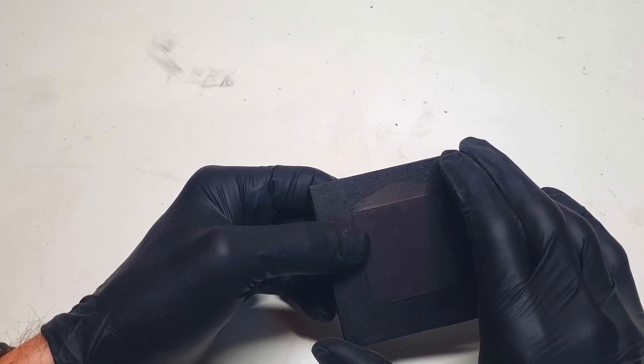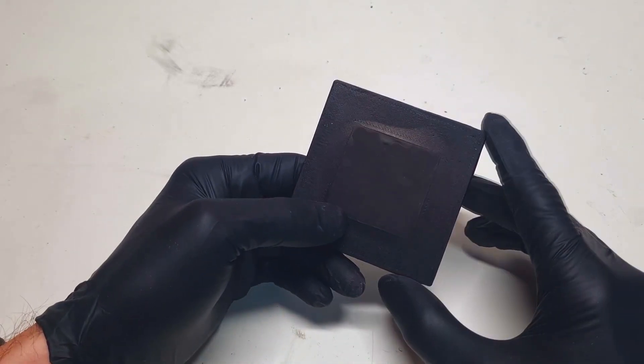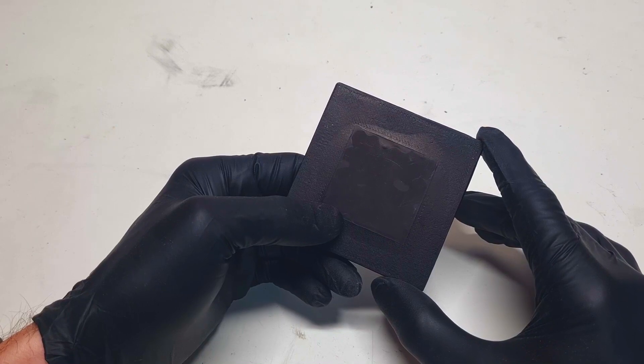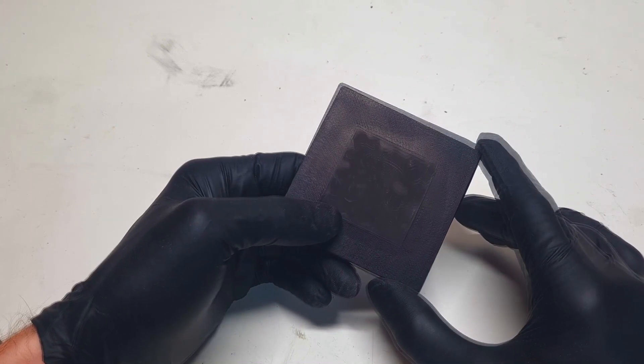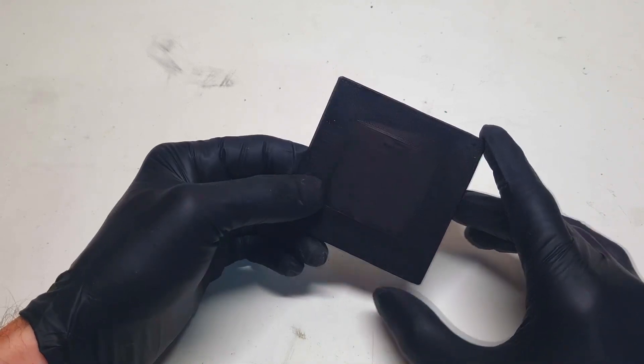Note: if you want to use PLA plastic for your battery housing, you need to use a neutral salt electrolyte. If you use an acid or alkaline based electrolyte, the acid or alkaline would damage the PLA really easily and you will get leakage everywhere.